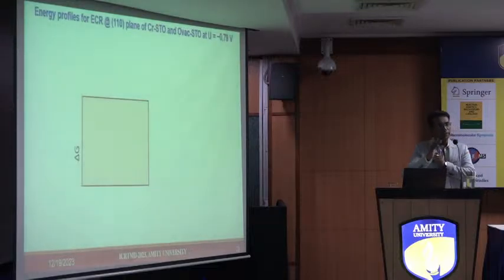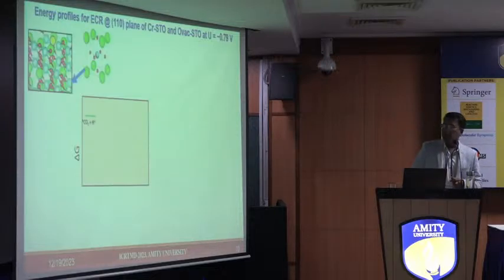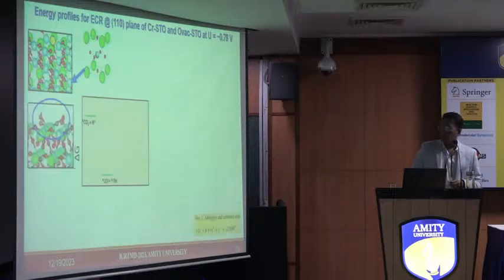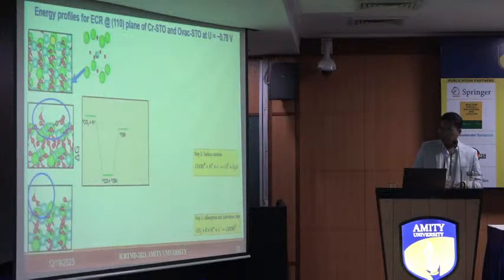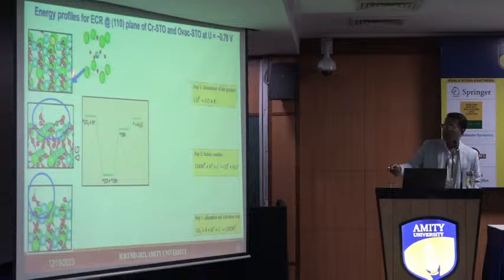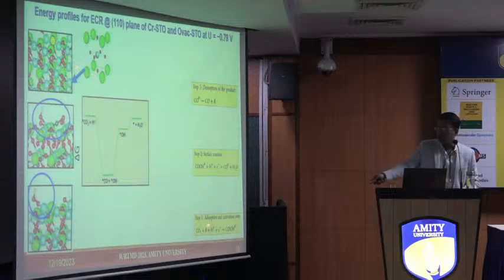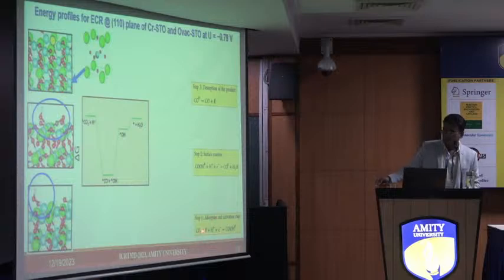So to understand what is exactly happening and why there is an increase in the yield of carbon monoxide, we shifted to DFT theory, in collaboration with Professor Dibyajyoti Ghosh in the chemistry department of IIT Delhi. I'll show you this first. This is the CO2. The carbon dioxide is coming on the surface. As soon as the carbon dioxide comes on the surface, this is the corresponding reaction. It is getting adsorbed on the surface.